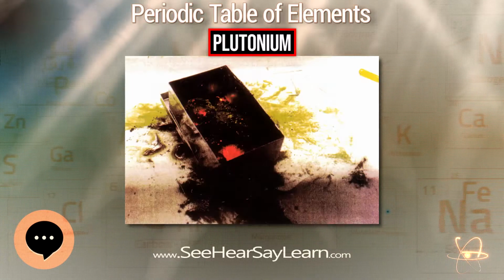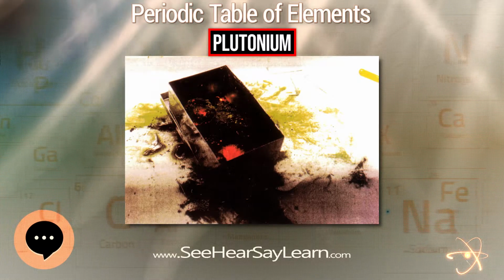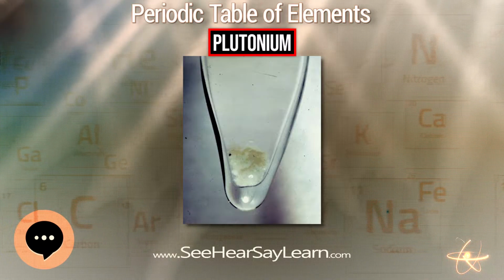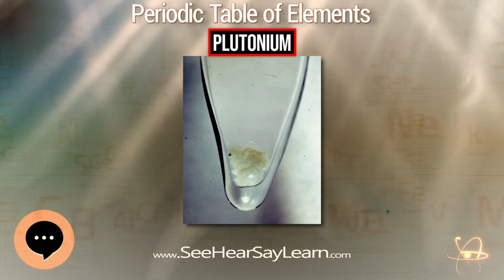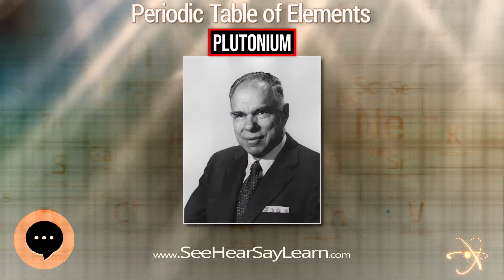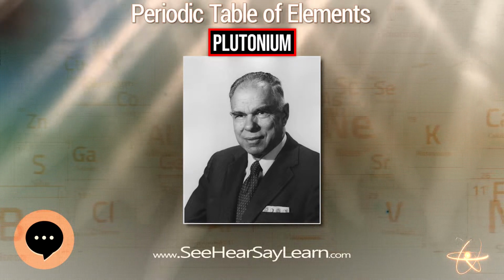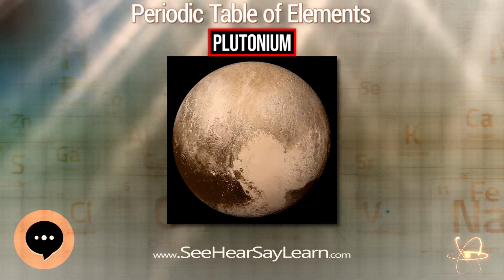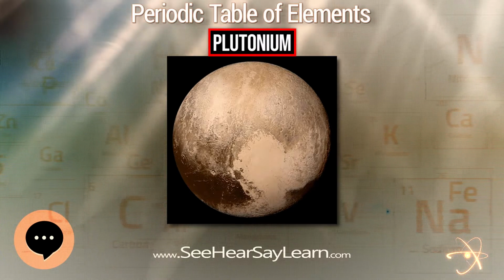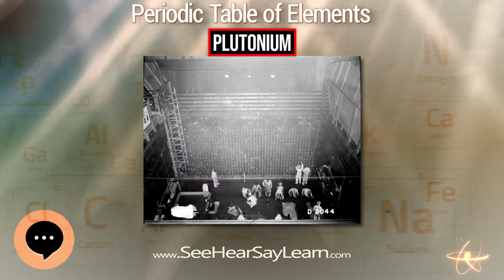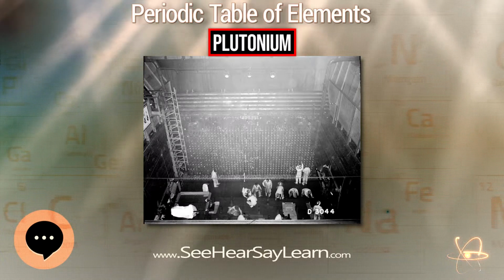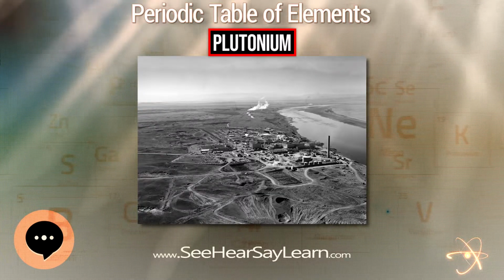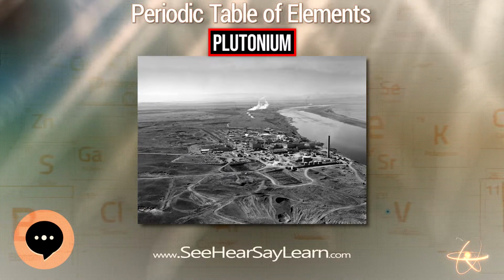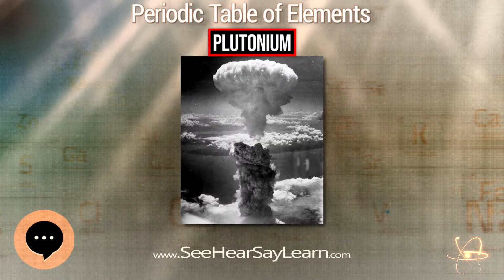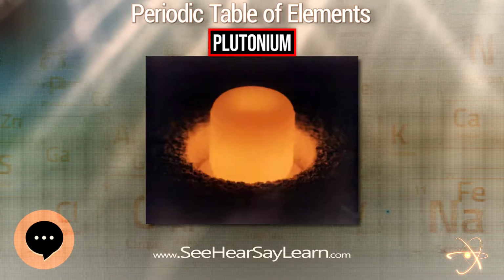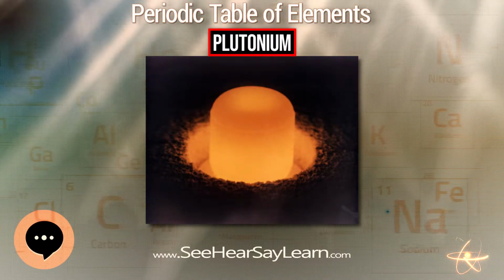In moist air or moist argon, the metal oxidizes rapidly, producing a mixture of oxides and hydrides. If the metal is exposed long enough to a limited amount of water vapor, a powdery surface coating of PuO2 is formed. Also formed is plutonium hydride, but an excess of water vapor forms only PuO2. Plutonium shows enormous, and reversible, reaction rates with pure hydrogen, forming plutonium hydride. It also reacts readily with oxygen, forming PuO and PuO2 as well as intermediate oxides. Plutonium oxide fills 40% more volume than plutonium metal.